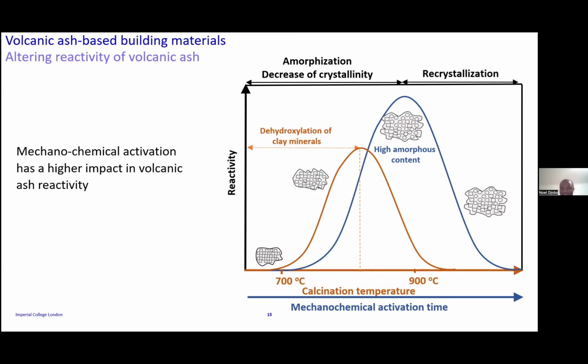And in the previous slide, I was trying to compare volcanic ash that had been used in natural state and clay that had been calcined. We have seen that the calcined clay was very reactive compared to natural volcanic ash. So some of the work has included the calcination of the volcanic ash, but the calcination was not quite efficient because in volcanic ash, you can also have some clay mineral. And during the calcination process, the clay minerals are being decomposed. That's what increased the reactivity.